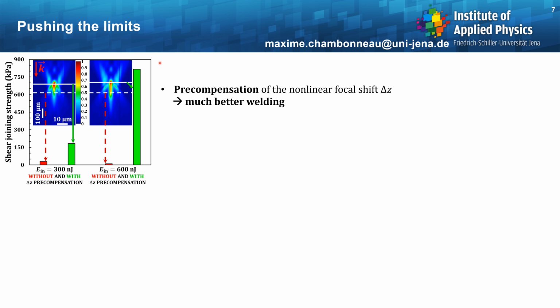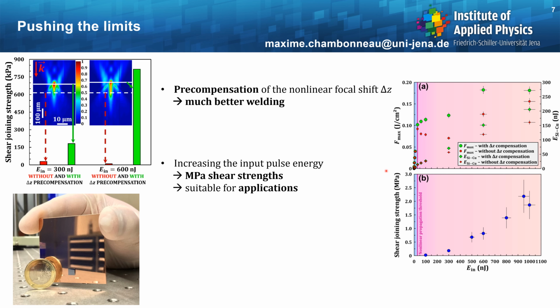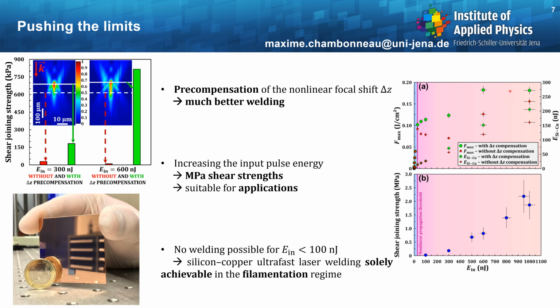Okay, so now what if we increase the input pulse energy but keep this delta Z precompensation strategy? Well, the results are essentially shown here in terms of shear joining strength as a function of the input pulse energy, and we can reach around 2.2 megapascal shear joining strength, around 1 microjoule, which is quite okay for applications. And this is explainable by the fact that both the maximum fluence and the energy reaching the interface are increased when you precompensate delta Z. Noteworthy, there is no welding possible when the input pulse energy is lower than 100 nanojoules here, which means that silicon copper ultrafast laser welding is solely achievable in the filamentation regime.